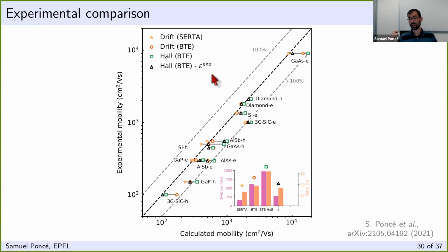One reason is the fact that we are computing the electron-phonon matrix elements at the DFT level. And because of DFT, we are over-screening, so the dielectric function is usually bigger than experiment. What I have done here, and this is not fully ab initio, is to rescale the electron-phonon matrix elements with the experimental dielectric constant. Those are the black triangles. Systematically, this will decrease the mobility, bringing it a bit closer to experiment.